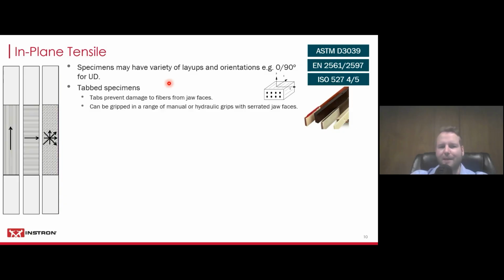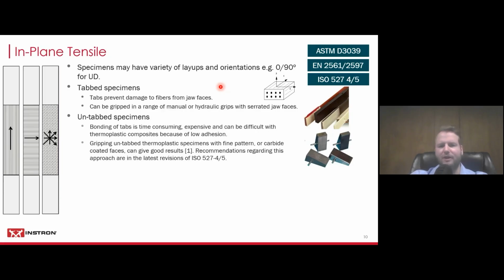We typically deal with tabbed specimens. It's really interesting to see the poll results because thermosets are still clearly the most used matrix materials, which also kind of helps with this because tabbing does prevent damage to fibers from the jaw face when you engage your grips to the specimen. And you can grip composite specimens that are tabbed with a range of grips that are either manual or hydraulic and with normal serrated faces. But tabbing is really time consuming, it's expensive, and it can also be really, really difficult. It's really kind of a science, and there's some really good material out there on Composites World magazine to help you get started on that.